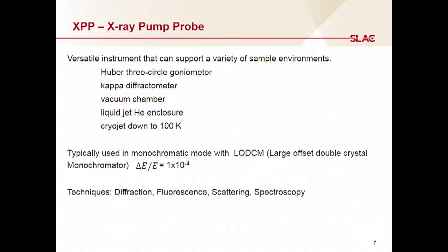The XPP experiment is typically used in monochromatic mode. There's an LODCM, which is a large offset double crystal monochromator. That's 2 silicon 111 crystals. And so you have very good monochromaticity, delta E over E, about 1 × 10⁻⁴. So that means about 1 electron volt, a few electron volt bandwidth.